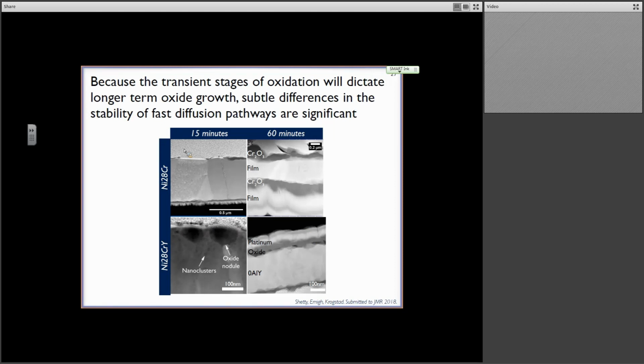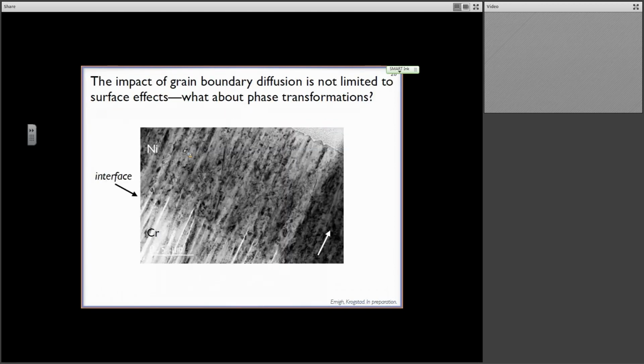Okay, so while the yttrium and the microstructure are changing rapidly, there is something in this transient stage of oxidation that is quite critical to the overall oxidation behavior and then the longevity of the component in oxidizing environments in general. So we think that there's actually quite a lot here in terms of understanding and using the microstructure, even if we don't keep it long term, to improve the durability and the oxidation resistance of service components.